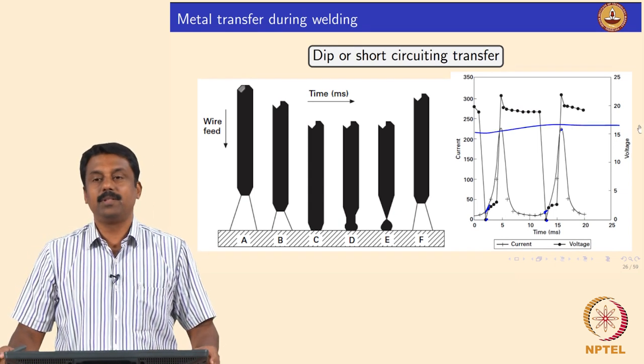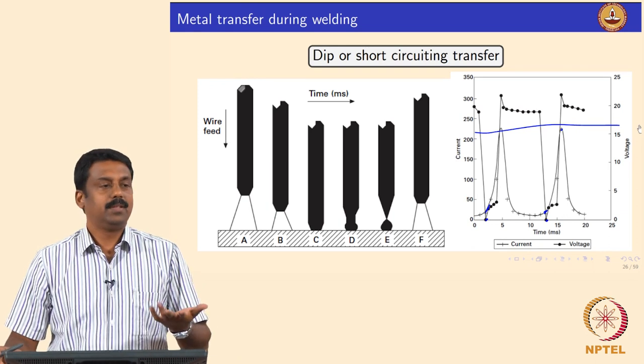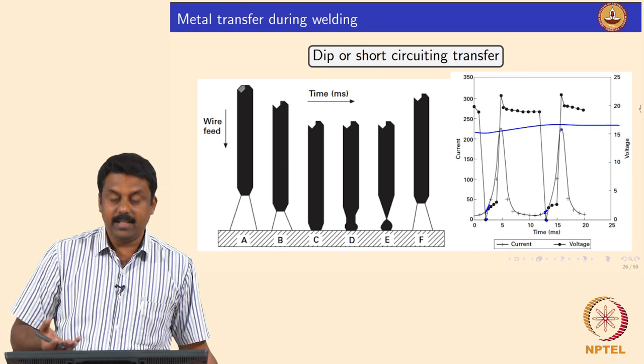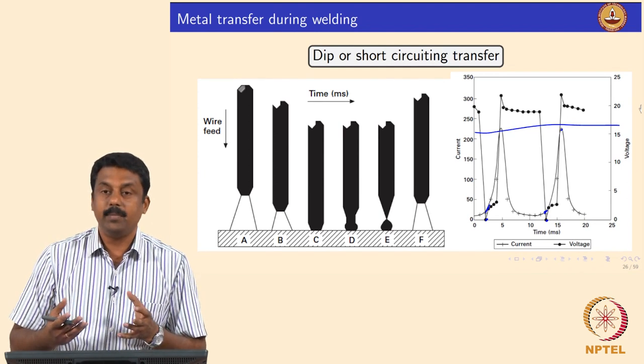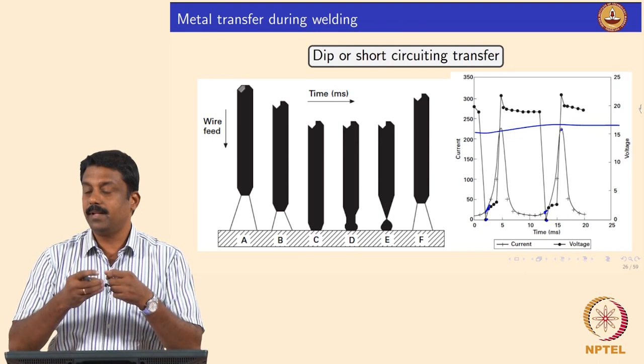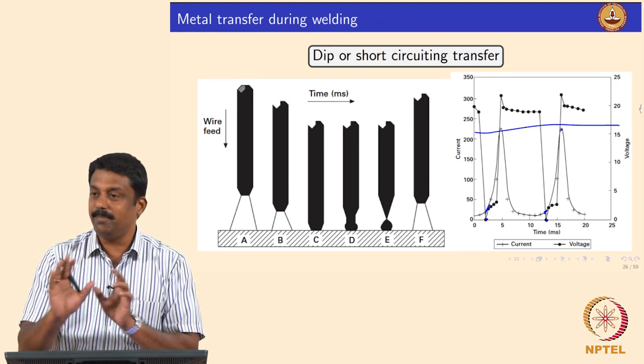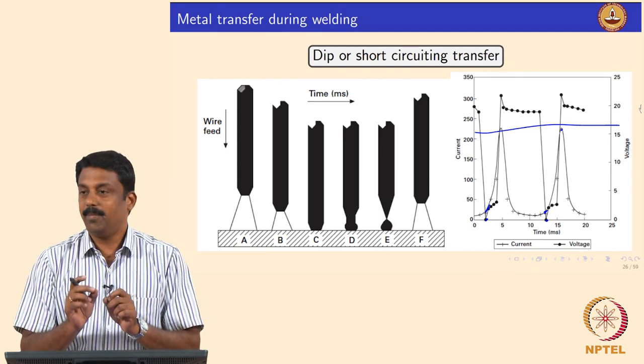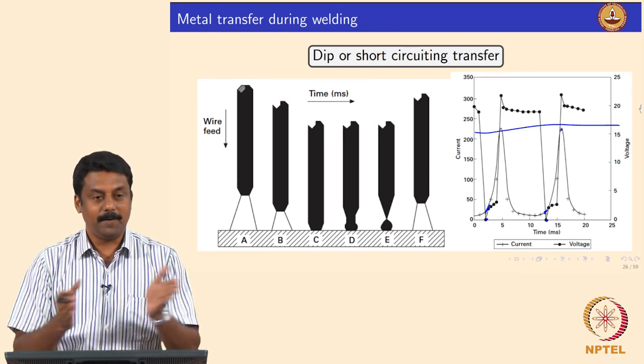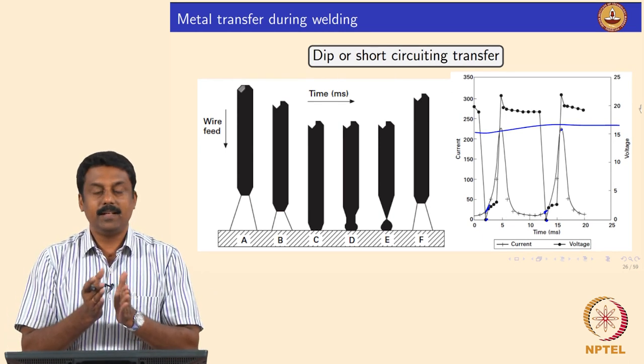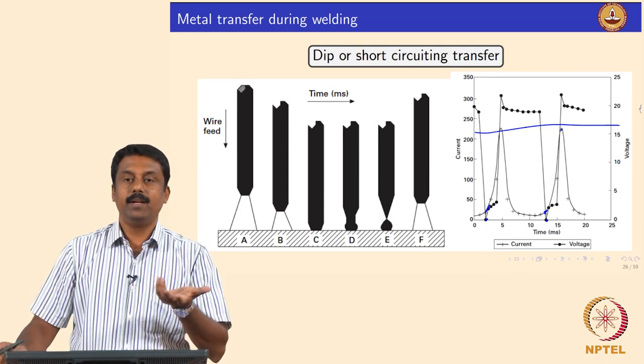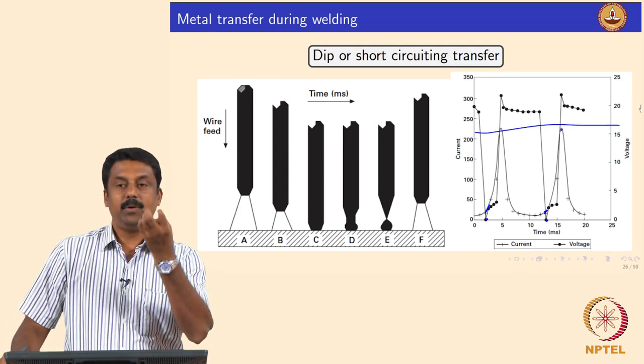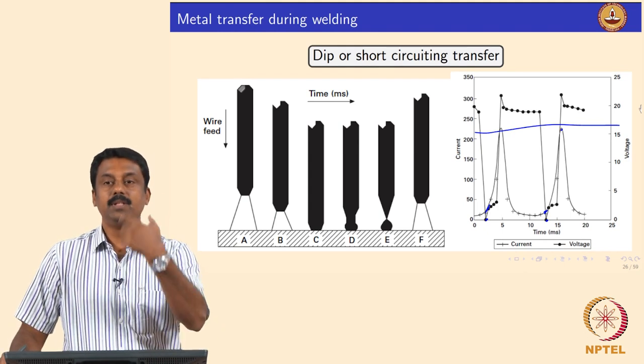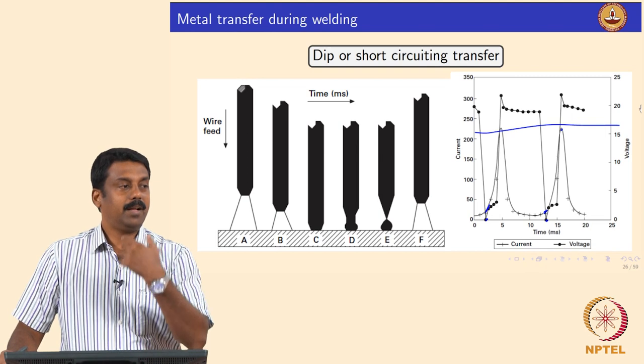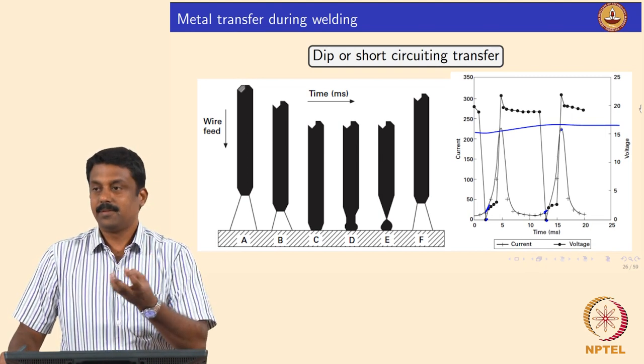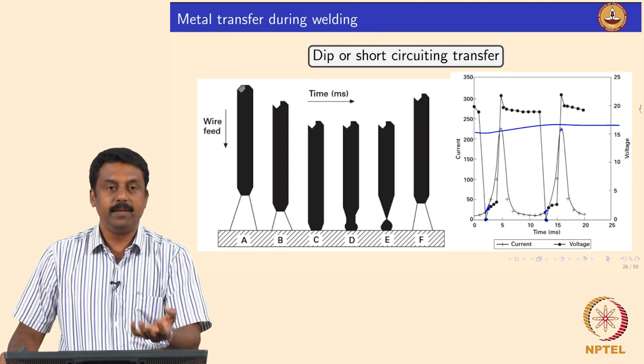So this technology is very widely used nowadays in advanced GMAW processes under various names. One of them is cold metal transfer. One of the technological advantages here is that the heat input can be reduced significantly, because when the droplet is transferred, technically you transfer it at the melting point of the droplet, is it not? And the arc is not continuously on, right? So even in the pulsing transfer, the droplet is transferred at a much higher temperature, okay, when you are doing a free flow transfer. The droplet temperature reaches the arc temperature, or rather it is superheated. So the droplet is transferred as a superheated liquid in free flow transfer.